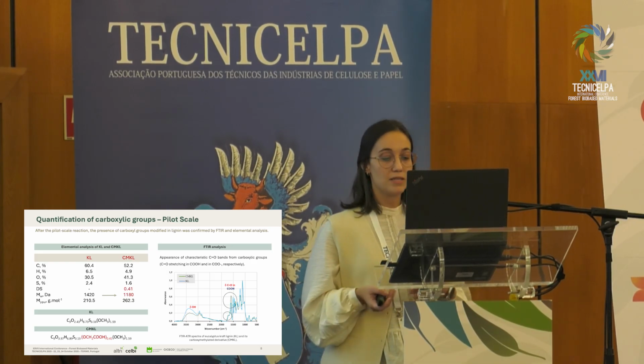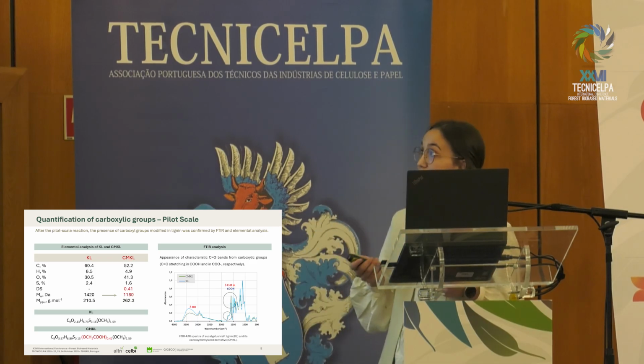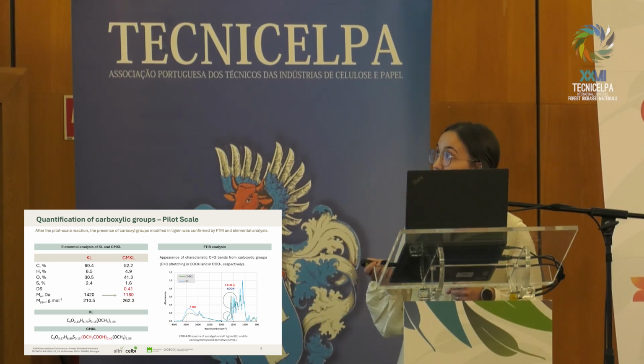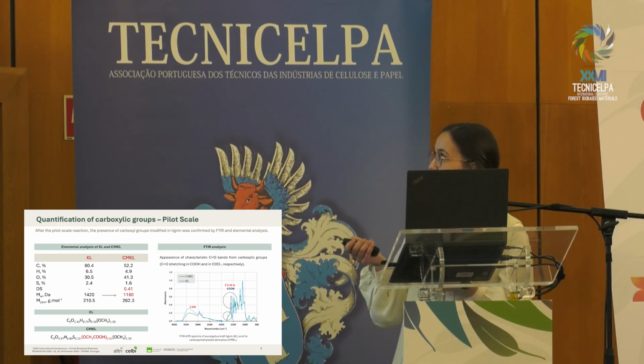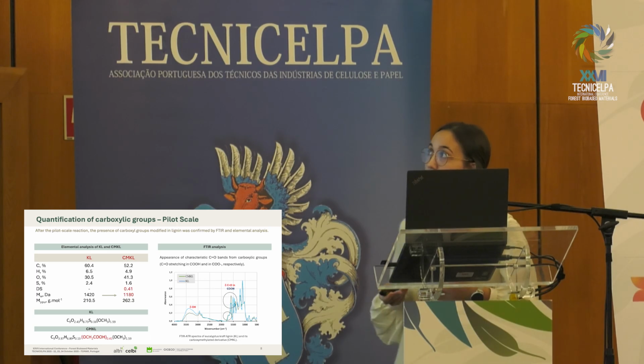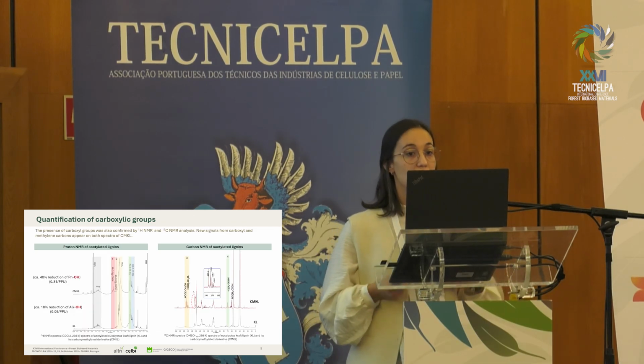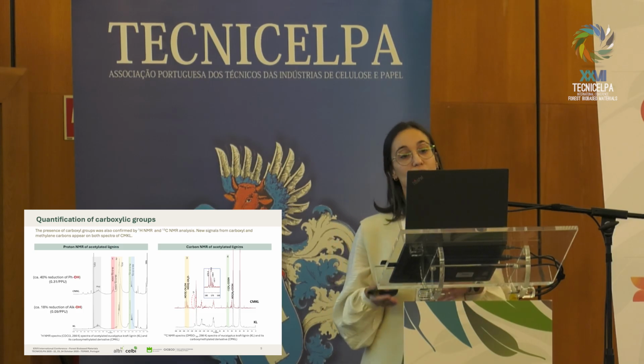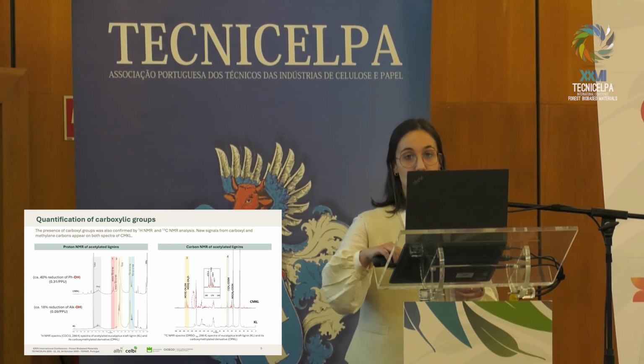So, starting with the lab scale experiments, we observed that the maximum degree of substitution was attained at 60 degrees. We also observed that higher sodium chloroacetate concentrations resulted in a higher degree of substitution. We don't see significant differences between degrees of substitution at different reaction times. And medium sodium hydroxide concentrations resulted in higher degree of substitution. So the optimal degree of substitution was attained at a temperature of 60 degrees with a molar ratio of sodium chloroacetate to KRAFT lignin of 3, sodium hydroxide concentration of 1.5 molar, and a reaction time of 2 hours.